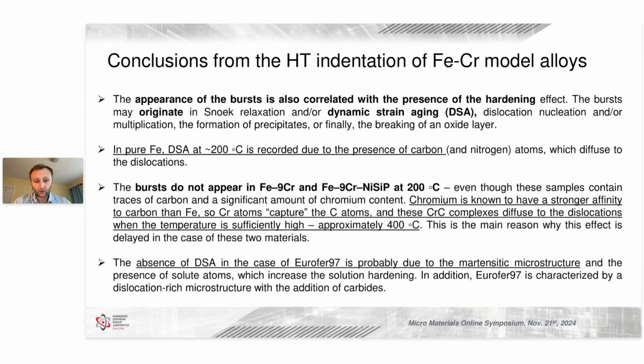The absence of those bursts in Eurofer 97 is related to the martensitic microstructure and presence of solute atoms in the Eurofer 97. This phenomenon is known as dynamic strain aging, and usually it is studied by using tensile tests. However, with this work, we proved that it is possible to use nano-indentation and demonstrate the presence of this phenomenon.